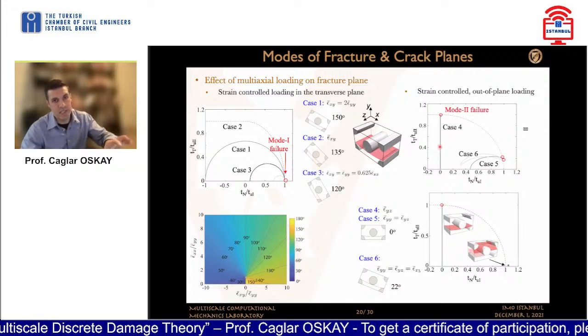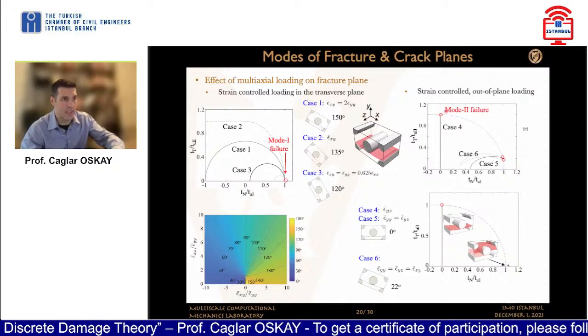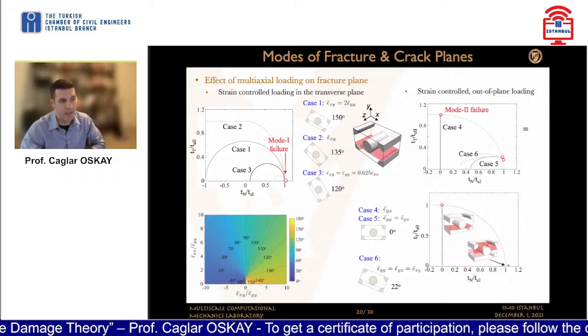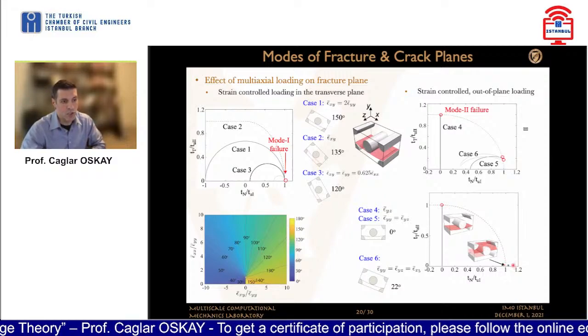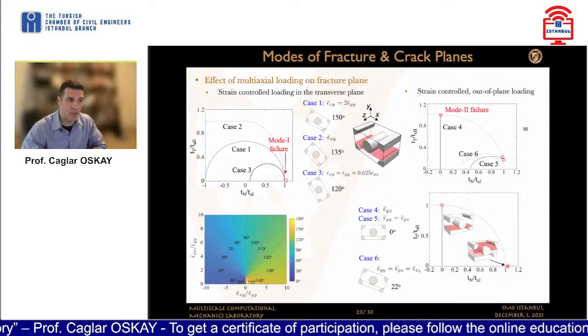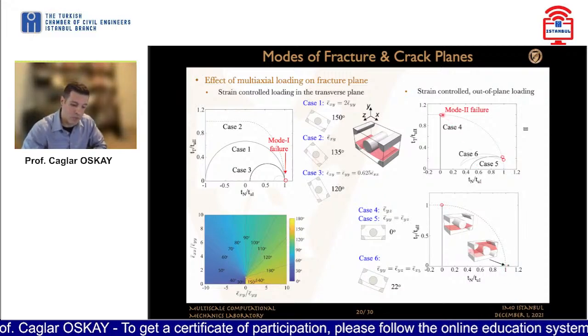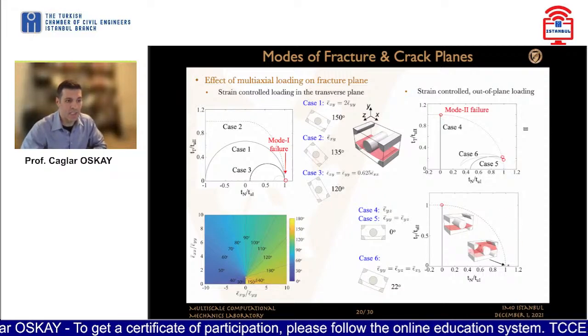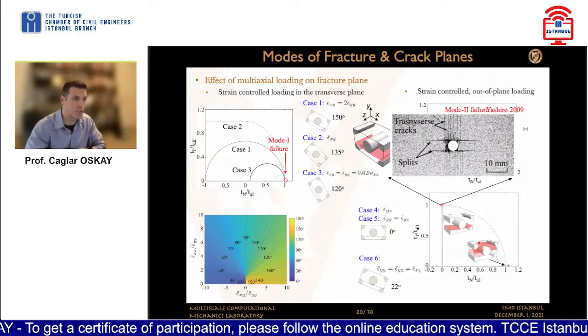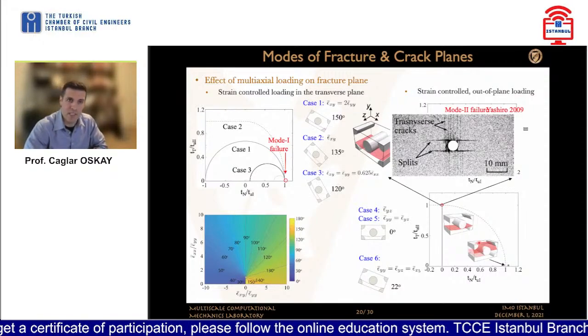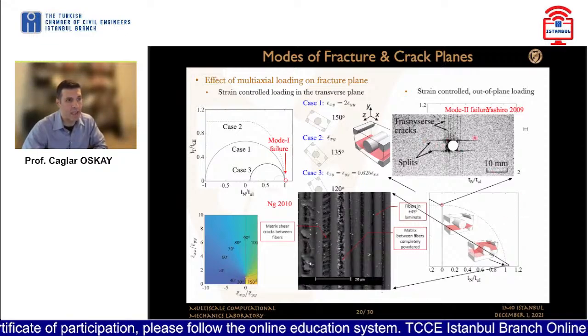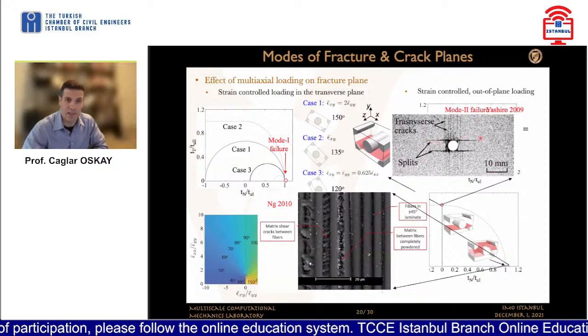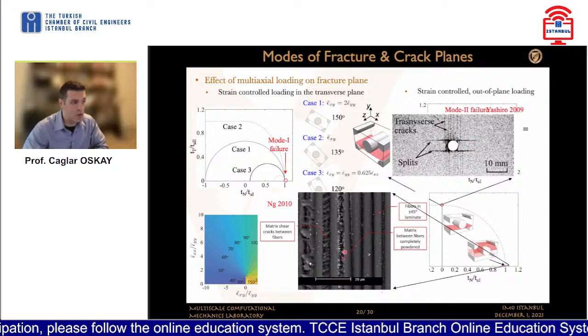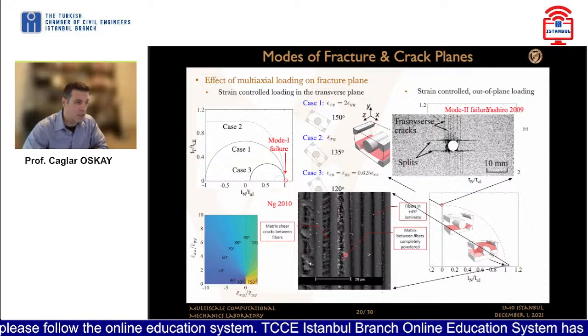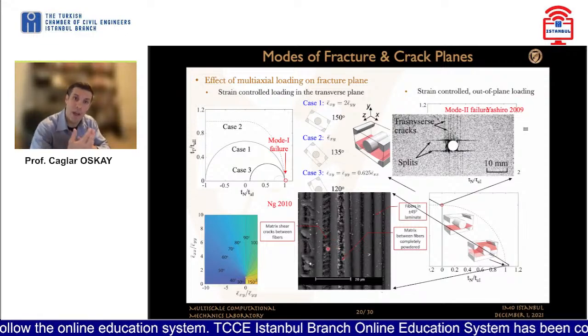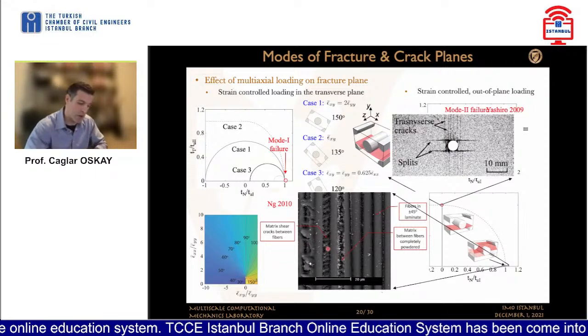So this, by the way, is physically very feasible. These two failure paths, the lower right-hand side figure in red, show a fracture plane that is a mode 1 fracture that occurs actually a little bit earlier than the ones that we are predicting, and that is a plane that is crossing the fibers, bridging the fibers. Now, these two failure planes are actually very easily observed in experiments as well. The pure mode 2 failure is a splitting crack, and the mode 1 failure that we're observing is the matrix shear observed in between fibers. So those are all possible modes that are observed in experiments.